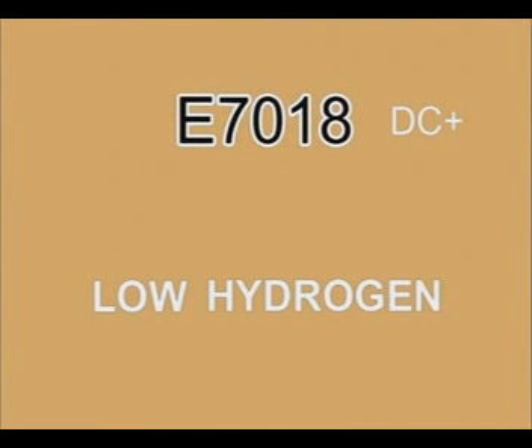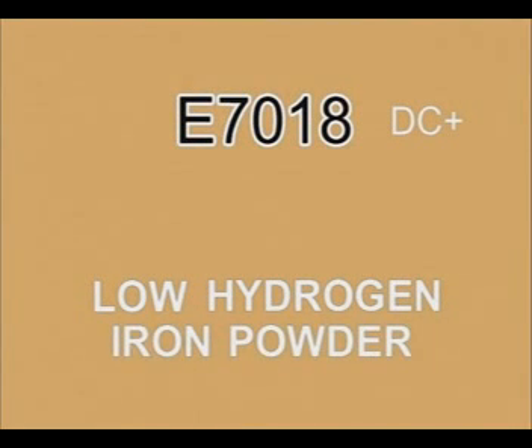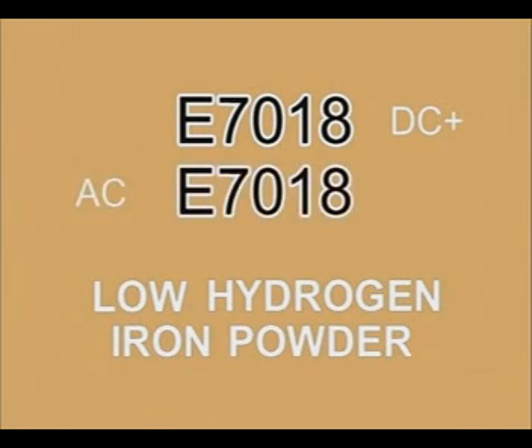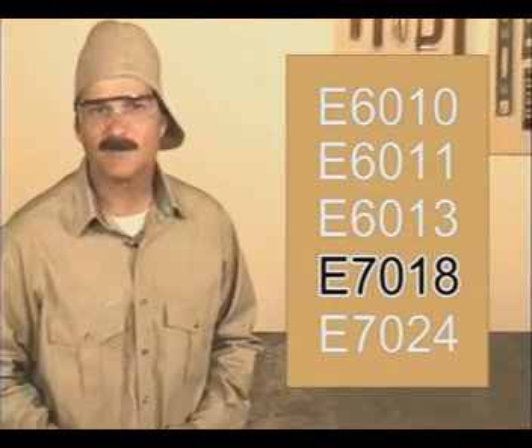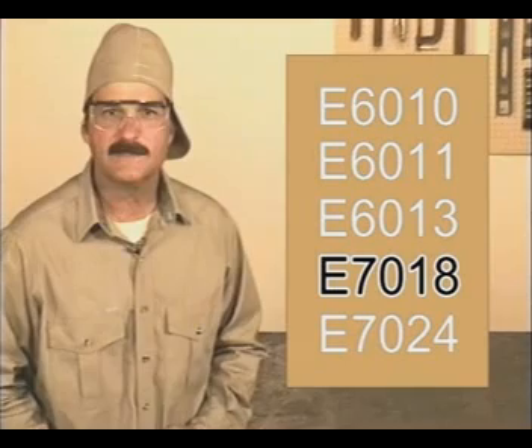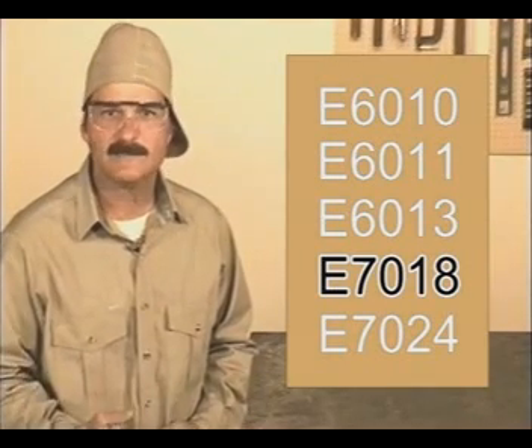7018 is a low hydrogen rod with iron powder in the flux. It's generally used on DC plus, and an AC 7018 is also available. These produce the highest quality welds and were developed for situations where there's extreme stress on the weld joint.